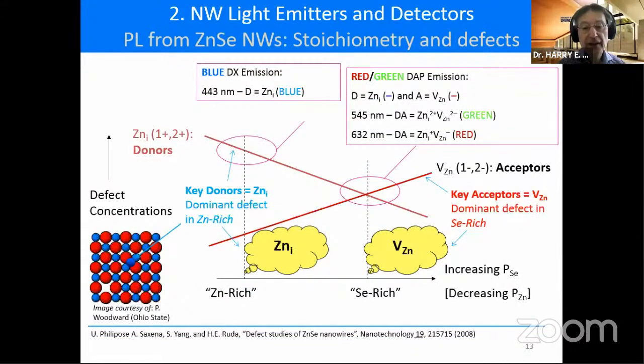Well, if you think of this graph here in the middle of the page, it's showing as an axis the selenium partial pressure increasing to the right. And when we do that, if you go through a Kroger-Vink analysis, we would be increasing the vacant zinc concentration, both singly and doubly ionized. At the same time, by increasing the selenium pressure, we would also be decreasing the zinc interstitial concentration.